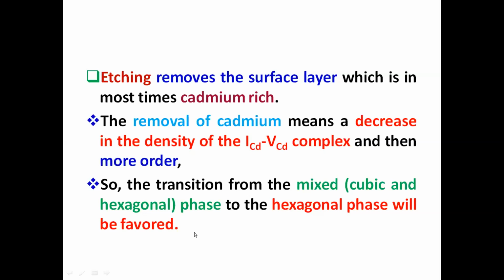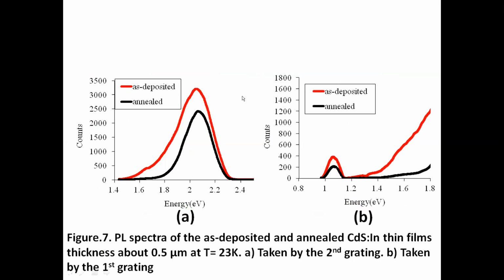Now here are the PL spectra of one film before annealing, as deposited, and after annealing. The black spectrum is for the annealed film, and the red spectrum is for the same film before annealing. As you see, the photoluminescence signal was quenched, its intensity decreased after annealing. You see this shoulder in the red region approximately disappeared after annealing, and in this part you see the red tail. The shoulders in the red tail approximately disappeared after annealing. These PL spectra are taken at a sample temperature of 23 Kelvin.